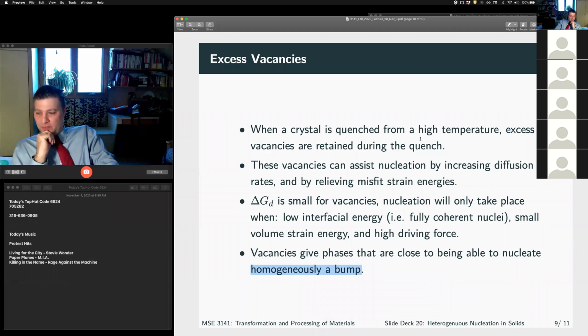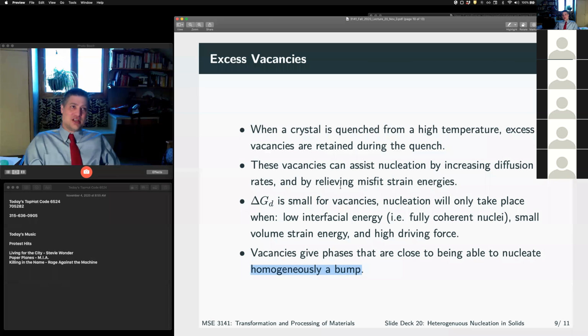Wait, I thought large vacancy helped heterogeneously. The vacancy, yeah. So what it does is, particles that would normally nucleate homogeneously, if there is a large vacancy concentration, they will nucleate faster. Whether you call it homogeneous nucleation in the presence of vacancies, or heterogeneous nucleation is kind of a semantic thing, right? But having excess vacancies is not going to help you nucleate large, complex secondary phases. It will accelerate your rate of nucleation of things that grow homogeneously or nucleate homogeneously,